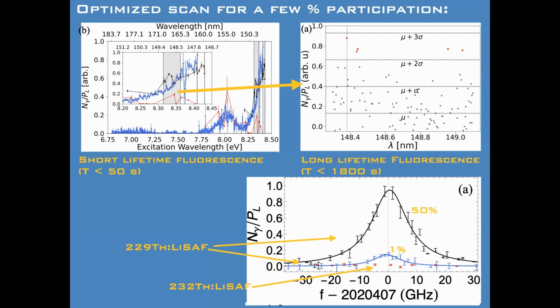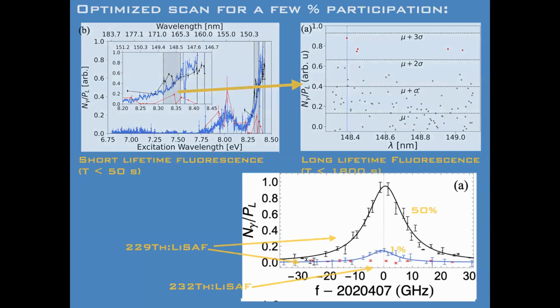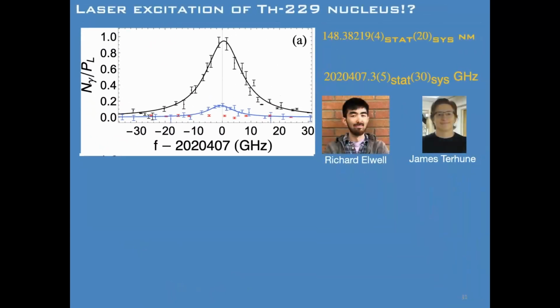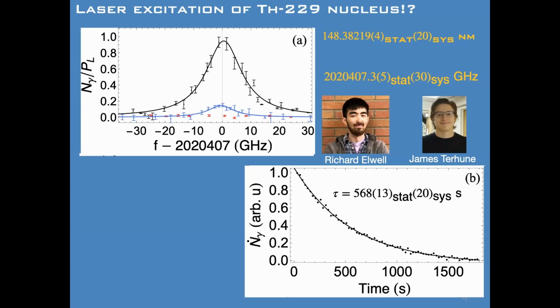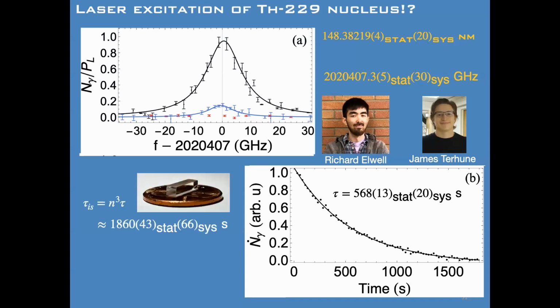Yeah. But nonetheless, this is really exciting now because we have something that could be the nuclear transition. So we can measure the frequency of this transition. We immediately went from nanometer wide error bars to 500 megahertz error bars. We can measure the lifetime of the state as about 600 seconds, just about what you would expect.